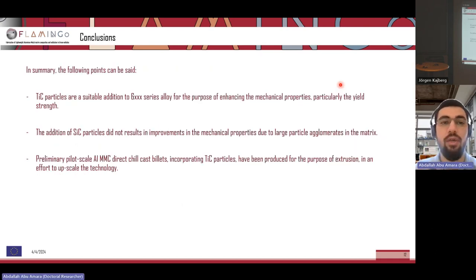So to summarize what's been mentioned, the following points can be said. Titanium carbide particles seem to be a suitable addition for 6000 series alloys, for the purpose of increasing the mechanical properties, and in particular the yield strength. And silicon carbide particles didn't result in the improvement that we saw with titanium carbide because the silicon carbide particles had agglomerated due to their smaller sizes. And preliminary pilot scale aluminium composite direct chill cast billets incorporating titanium carbide particles were produced, and these also were extruded successfully. And this is all in an effort to upscale and industrialize the metal matrix composites technology.